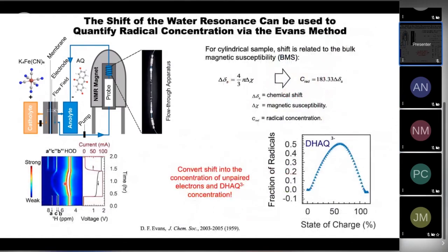And the first thing we worked out was that we could use the shift of the water resonance as simply a way of measuring the radical concentration via a very standard method called the Evans method, that's been used for many years by inorganic chemists to measure susceptibility. And that allowed us to quantify the radical concentration, which you can see in 50% state of charge only reaches